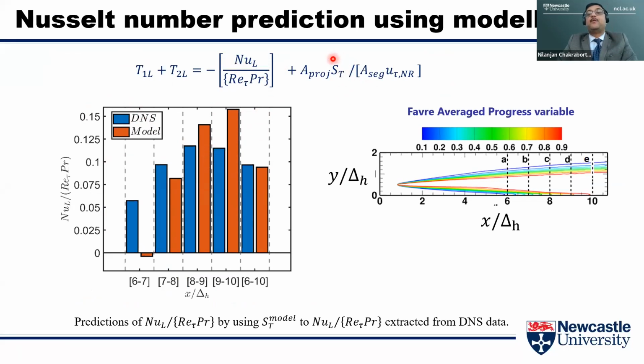And if I put the modeled expression of turbulent burning velocity as shown in the previous slide there, there can be quite a large discrepancy, especially towards the leading edge of the boundary layer. But when you integrate from here to there, the agreement is relatively good. However, that brings some uncertainty. In other words, it is probably not a good idea to estimate Nusselt number in the case of flame wall interaction based on the turbulent burning velocity.